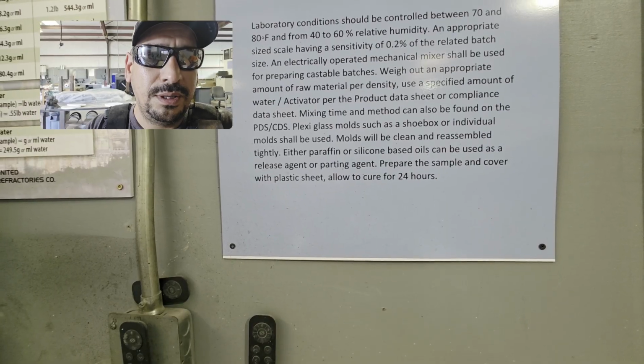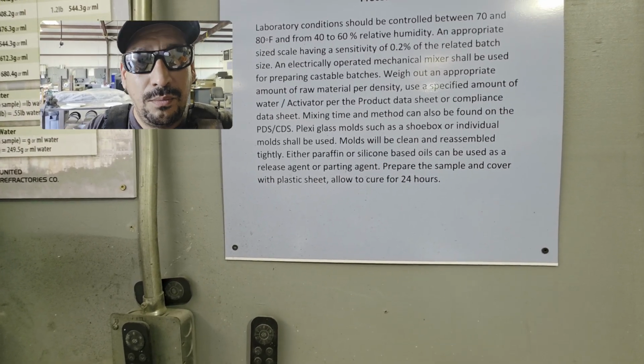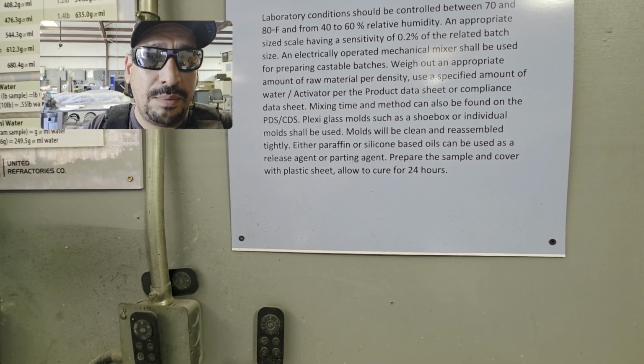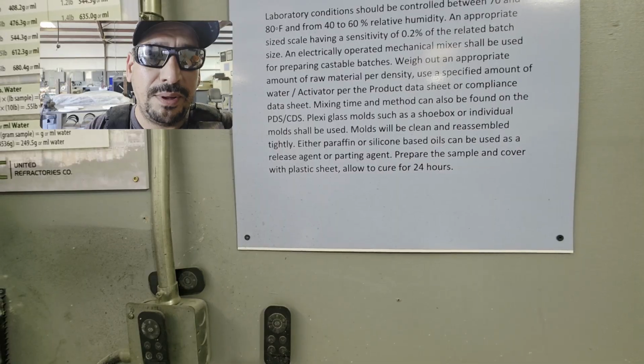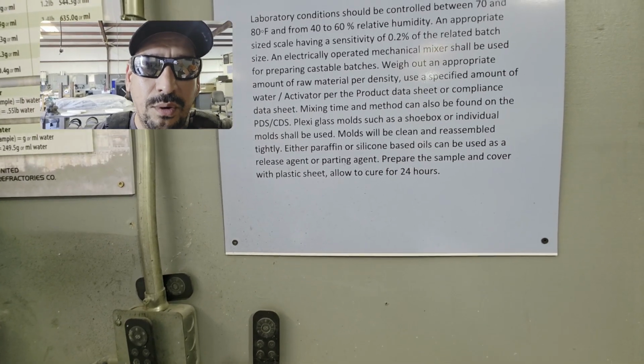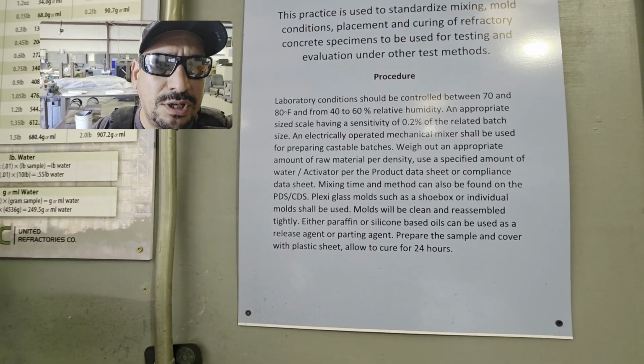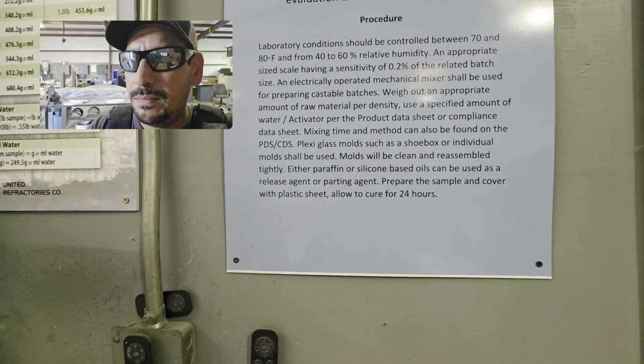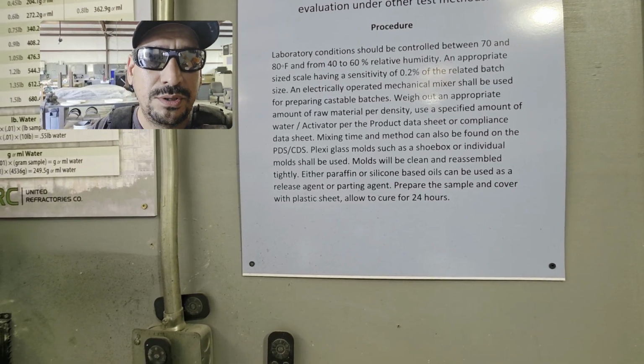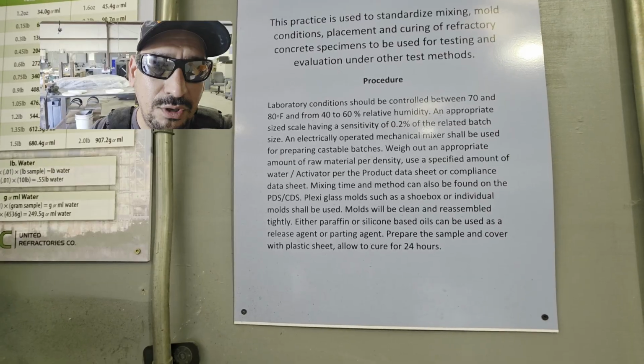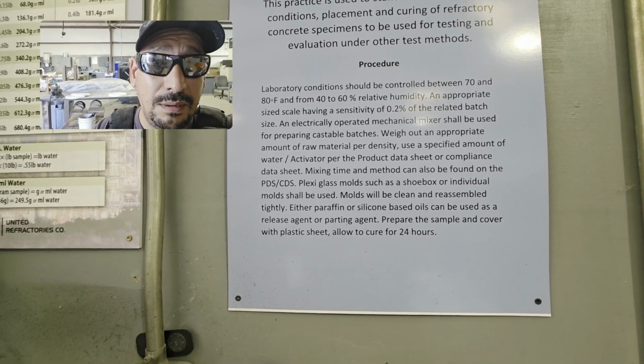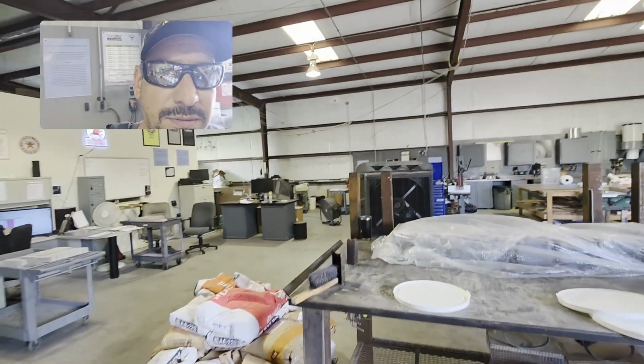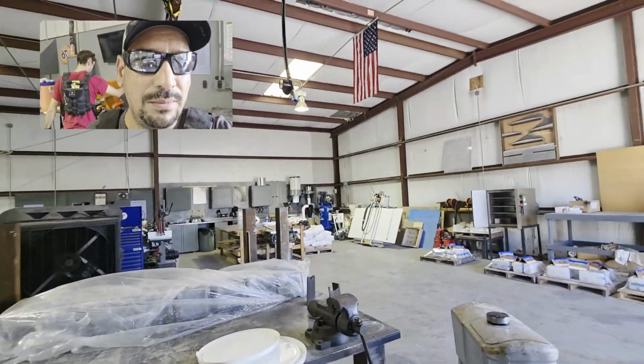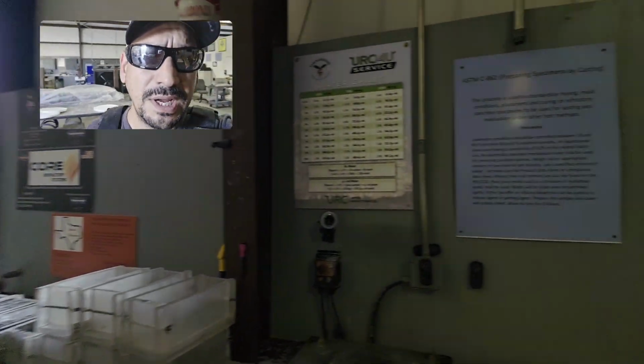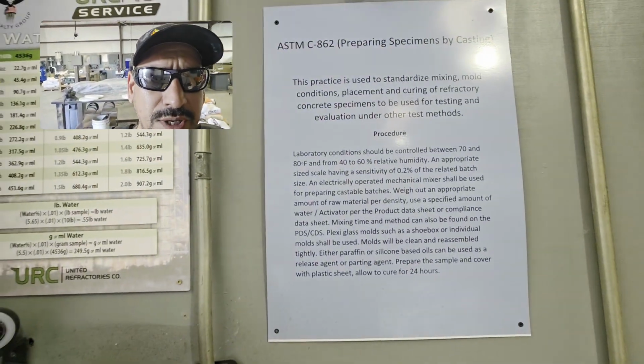And then, of course, you're going to leave your specimens in their molds with either curing compound, or in the lab we use a plastic trash bag, a sheet, a roll of plastic, and we allow it to cure for 24 hours. So just maintain your temperatures, and you can do that by controlling your material temperature and your water temperature. There's not always much we can do about that humidity, especially out in the field, or even in the lab. This is not an air-conditioned facility. This is just a warehouse, and so if they want to jump on us about that, they can, but most of the time they don't. But if it is one of the questions, let's keep that in mind.